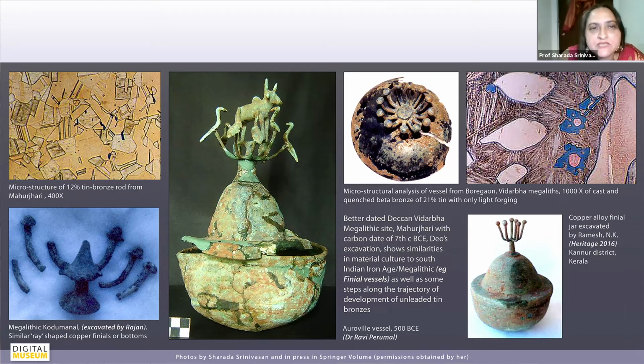We do have some better dates for the Vidarbha megalithic material, which was excavated by the Deccan College, by S.P. Deo and so on. For instance, Mahurjari gave a date of about 7th century BC. And at the top there, you're looking at a vessel from Borgaon, the Vidarbha megaliths, which I had also analyzed. And that is also a cast and quenched beta bronze. It has, in this case, not quite the 23% composition, but getting there, 21% tin. So it has an alpha plus beta composition. You see the dendritic alpha phase and then the quenched martensitic beta phase. But this is more lightly cast and quenched. It's not very heavily forged. But what is significant is that it points to this tradition going back to the 7th century BC.